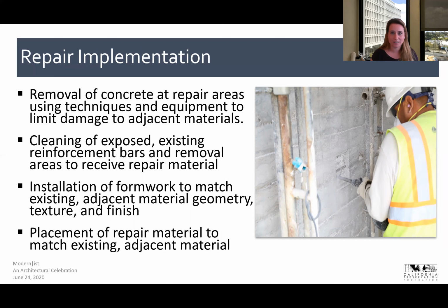You need to be able to access it to clean the bar, potentially install a corrosion inhibiting coating. But these really need to address why the deterioration is there. So yes, you may be removing sound material, install your formwork just as done in the mock-ups to match, and place the material just as was done in the mock-ups and finish it to achieve the desired appearance and finish to match the adjacent concrete.